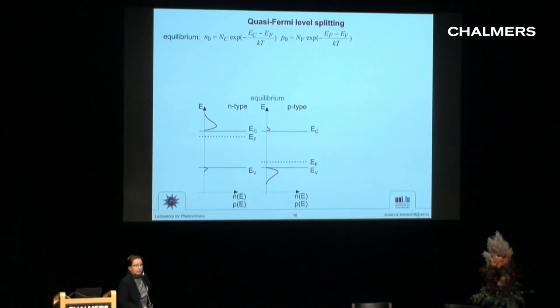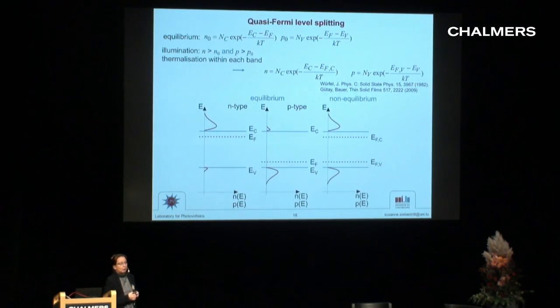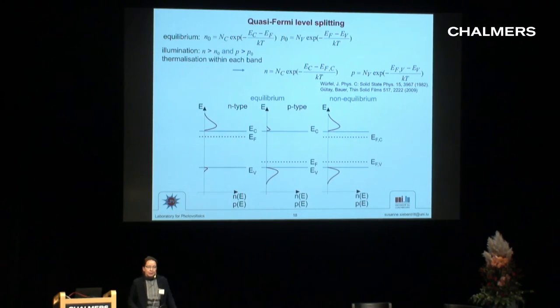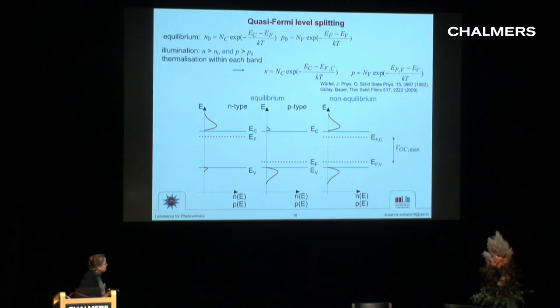Now, when we shine light on the semiconductor, we take electrons from the valence band and put it in the conduction band. So we generate electrons up here and holes down here. So the Fermi level at the same time would have to move up and down, which obviously is not possible. But because of the thermalization, we still have a decent distribution of electrons and holes in the bands, and we can define two Fermi levels, which are not real Fermi levels because there are two, and we call them quasi-Fermi levels. And this distance here gives us the maximum voltage that we can get out of the semiconductor. And we can measure that by photoluminescence.